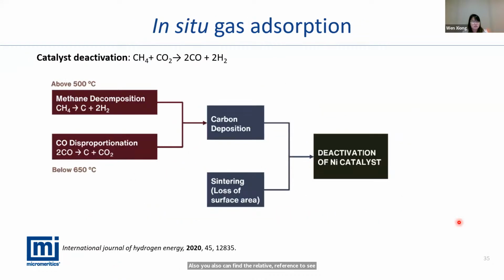Finally, I would like to introduce the in-situ gas adsorption characterization for catalyst. This is a new promoting method by Micromeritics, in-situ gas adsorption. Here I'm using the methane dry reforming reaction on the nickel catalyst as an example. As we always know, methane dry reforming is operated at a very high temperature, like 500 degrees C to 650 degrees C.